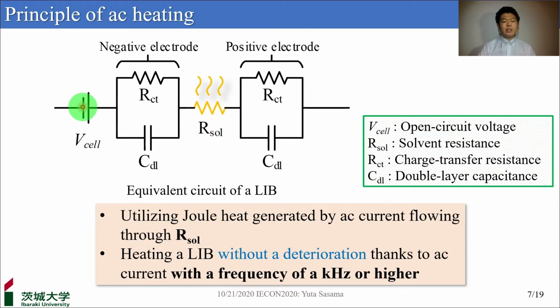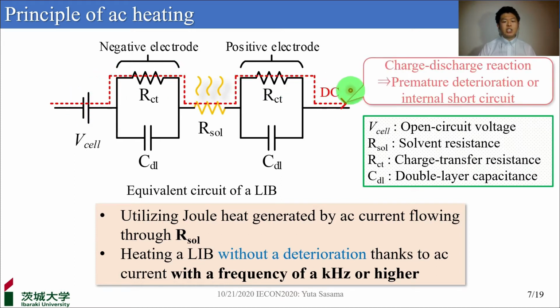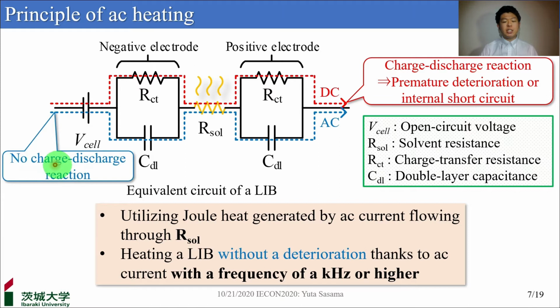When DC current is used, the current flows on the red dashed line and the charge-discharge reaction takes place. The charge-discharge reaction at low temperatures brings about premature degradation or internal short circuit due to lithium deposition. On the other hand, the AC current with a frequency of a kilohertz or higher flows on the blue dashed line. This route doesn't accompany the charge-discharge reaction, so AC heating can heat a battery without degradation.